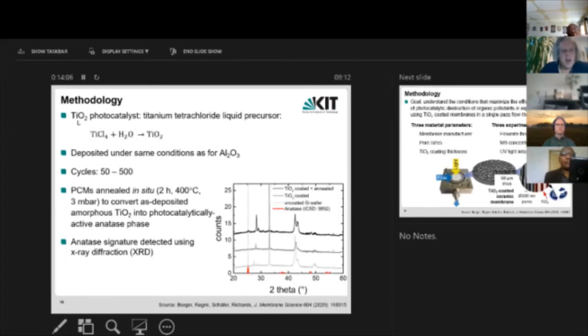The key material for our work was titanium dioxide as the photocatalyst, and for that we used a titanium tetrachloride precursor. So here again, it's just the simple reaction with water forming our titanium dioxide. The deposition conditions were the same as I described before, so 250 degrees C is the substrate temperature, and we're doing somewhere between 50 and 500 cycles of this material. Now, because the temperature is relatively low, this gives us an amorphous titanium dioxide, which we don't want. We would prefer the more photocatalytically active phase of anatase, and that we achieve by annealing at 400 degrees C in situ. So after the deposition is done, we raise the chamber temperature up to 400 degrees C, giving us a conversion to the anatase phase.